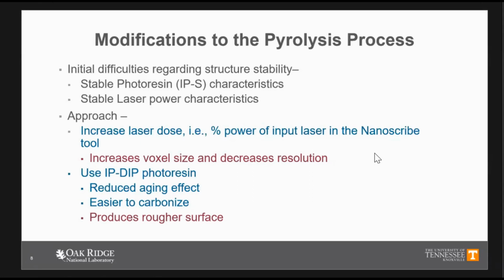And the use of IP-Dip was another comparison we wanted to try compared to IP-S. We have seen that it has a reduced aging effect for the same batch that was purchased for IP-S and IP-Dip. And it is easier to carbonize with a shorter duration of the high anneal time. But the problem is that it is much less smooth than IP-S structures, so it can also have inconsistent sizing between your structures.